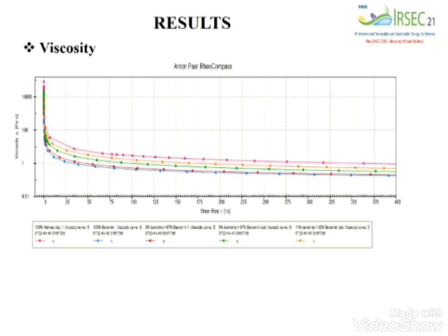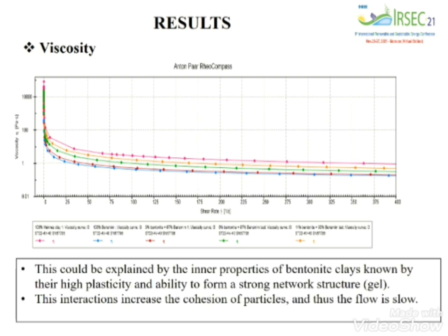We can notice also that the addition of bentonite increases the viscosity of the Bensmim sample, making it close to the reference sample, which is the Extrabrick sample. This could be explained by the inner properties of bentonite clays, known for their high plasticity and ability to form a strong network structure, which is also called jelly structures. These interactions increase the cohesion of particles and thus the flow is slow.